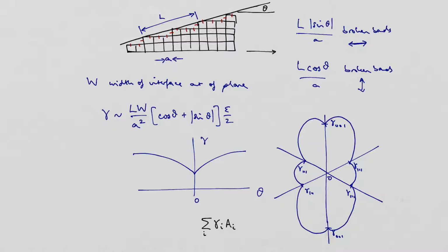Well, the Wulff construction says you find this by drawing lines from the origin to points on this gamma plot, and then you start drawing planes perpendicular to these. You imagine doing that for every single thing that you can. Then it turns out, and it has been proved, that the thing that minimises this quantity is a construction where you choose the shape that is inside all of those planes.